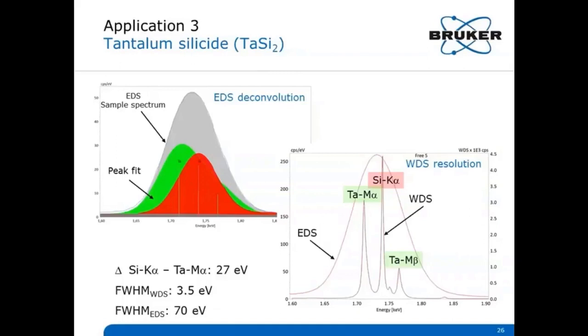At first, we have a look on a spectrum from a point analysis. Tantalum silicide shows a pathological EDS peak overlap between the tantalum M lines and the silicon K lines. These lines are only 27 electron volts apart and cannot be resolved by EDS, but they can be deconvolved.